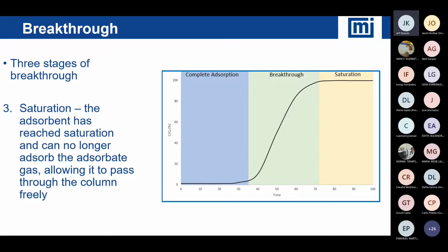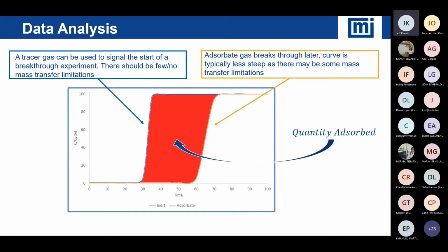So conceptually, the breakthrough experiment is quite simple. We're going to flow gas where we know the concentration. We're going to monitor the concentration as it comes off of the sample. Okay. We typically use a non-adsorbing gas in the mix. The non-adsorbing gas is used because that helps us understand just simple flow through the sample bed, right? That basically tells us, well, I started flowing helium and I started flowing CO2 at the same time. When do I see helium? When do I see CO2? The difference between the two, very nicely, is the quantity adsorbed, and that's what's in red.